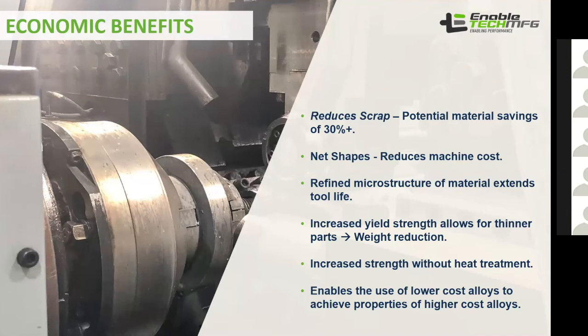The refined microstructure gives you some extended tool life, increased yield strength, which allows that part to have better pressure ratings, but also weight reduction. I know it's not always something we're looking for in oil and gas, but hydraulic cylinders and things like that, believe it or not, on some of the big tractors and stuff, they are trying to reduce weight. And then also this enables us to lower alloy costs by achieving properties that you would only be able to get through higher cost alloy. So in an example, there are situations where we've used C22 in lieu of MP35N. We have a $16 a pound alloy instead of a $90 a pound alloy.